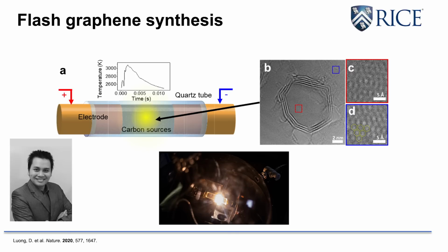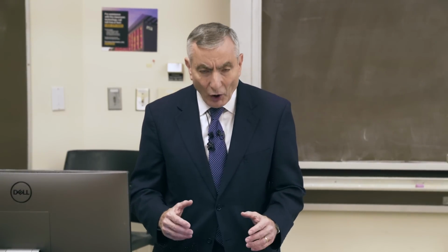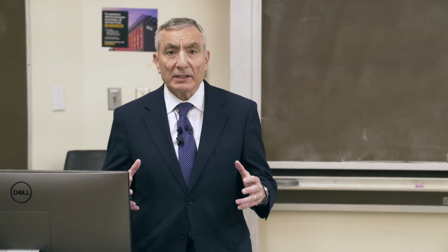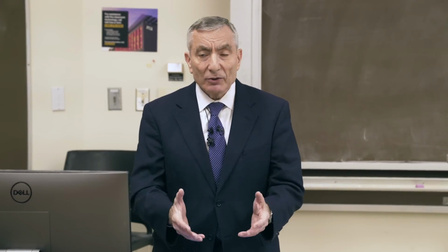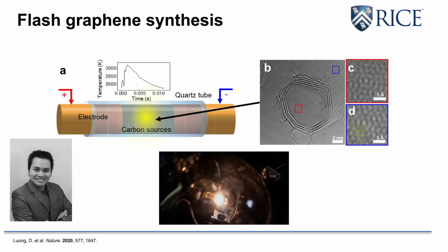Any carbon source is put between two electrodes, you apply a high voltage and a high current. It heats to over 3000 Kelvin in about 3 milliseconds. It heats at about 10^5 Kelvin per second, and it cools at about 10^4 Kelvin per second. What happens is you're pumping in enough energy that every bond in there just breaks. Then it reassembles, and the thermodynamically most stable form of carbon is not diamond, but graphene. And it reassembles as graphene. You get a big flash of light in the process. This is black body radiation, and you get graphene. So you get these graphene sheets coming out, and this is clearly nice graphene. This is what Tour had discovered.